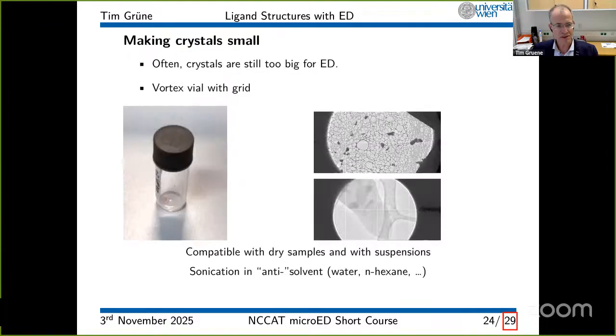And maybe one more thing on the previous slide. Another thing is when you look at these grains, a trained X-ray crystallographer would probably not consider them as crystals because they're so irregular. When you look at crystals under the electron microscope, they lose their typical crystalline shape. They don't have very sharp edges usually, and often the really ugly ones, they're the ones that diffract best. So as a take-home message from a practical point of view, don't discard a crystal because it looks shabby. Always go into diffraction mode and check if it really diffracts, because the shape does not tell you very much about the quality of the diffraction pattern.